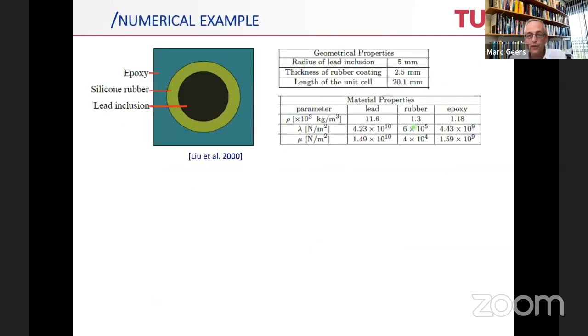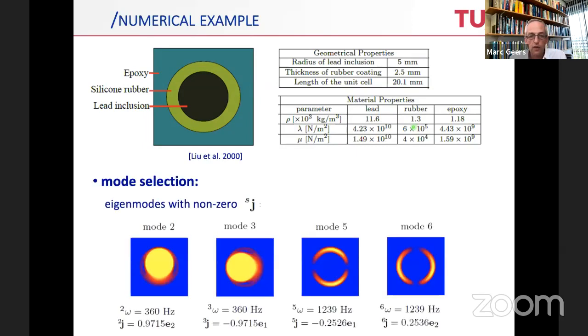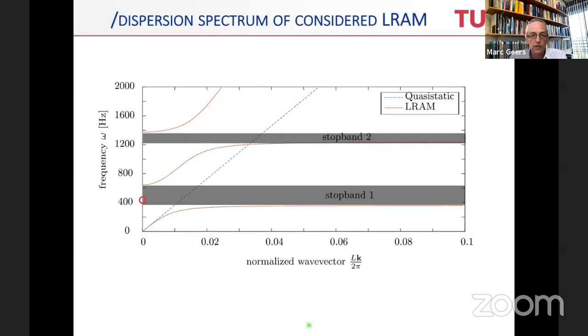We go back to that Liu example, for which the experiments were done in 2000. Here is the mode selection. You solve the eigenvalue problem and you select modes. As you can see here, the modes are selected based on the magnitude of the J coupling vector. That governs which modes are really important for this particular problem. Once you've done that, you can set up a dispersion spectrum. The dispersion spectrum shows us the different branches and which waves can propagate. So we see two stop bands here.